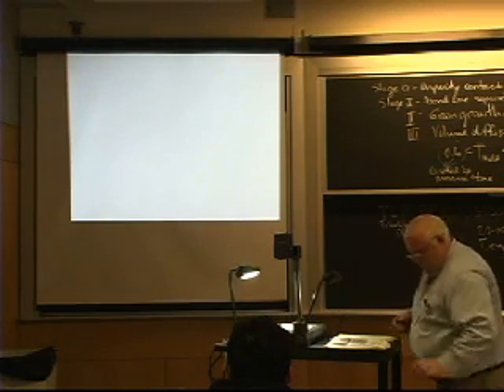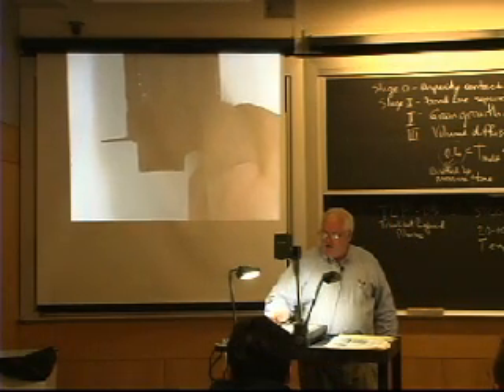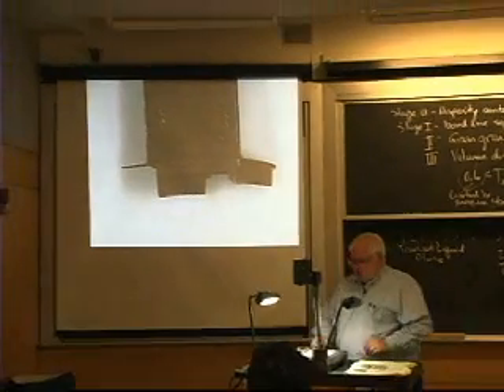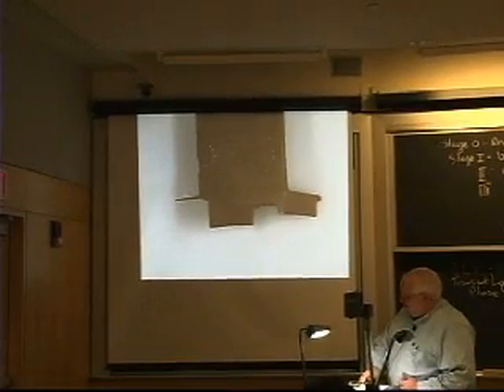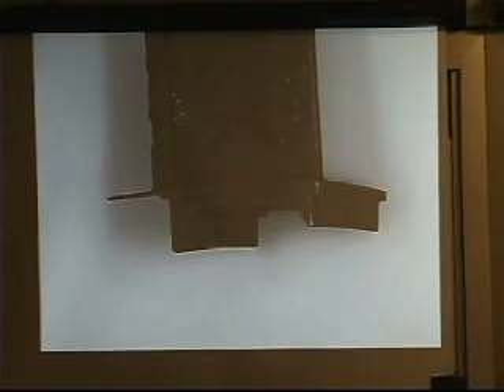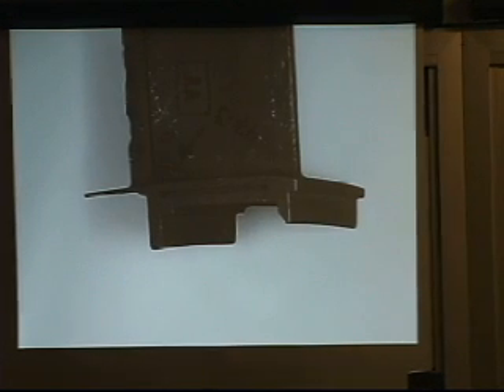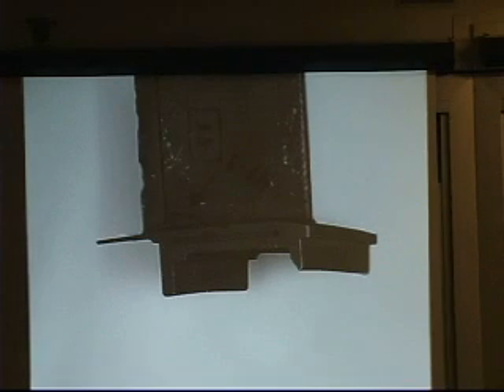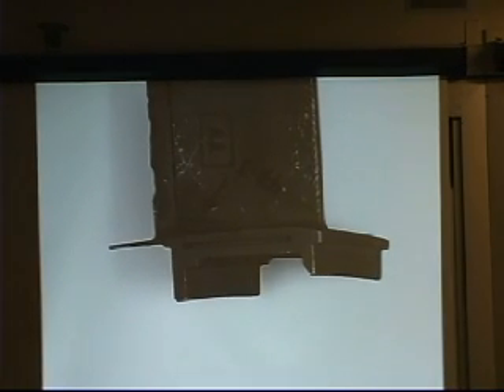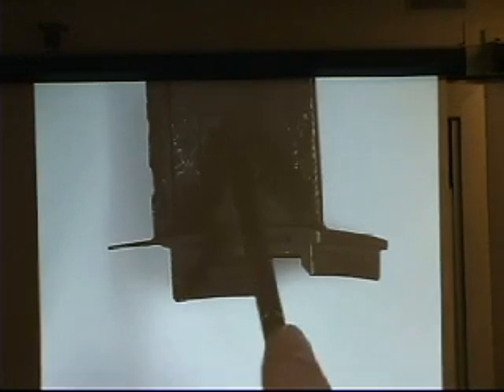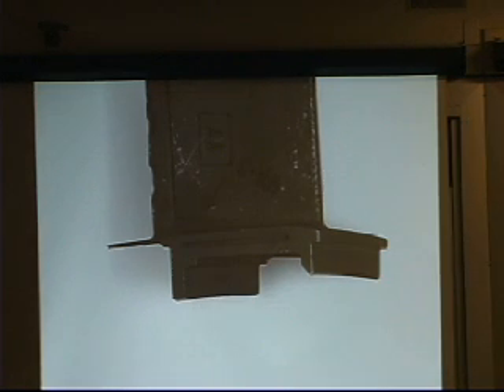Okay, to give you an idea of what people use this for, they use it for lots of things now. It's been expanding dramatically. Back in the 70s, and when I started lecturing this course in the mid-80s, I used to say this is a process that's specialized for nickel-based superalloys. But this is a turbine blade that developed some cracks from service. They're thermal expansion cracks. This part of the blade up here, the vane, is hot, and the root down there is cold, so I have a temperature difference across here. If you cycle this enough times, turning your engine on and off, you'll develop cracks.